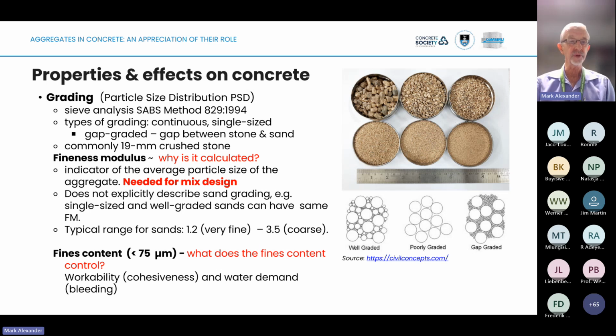We then have fineness modulus. This is an indicator of the average particle size. We need it for mix design. But note that it's not an explicit measure. You can get fineness moduli for different sands of the same value, but they might have vastly different gradings. And so it's a general sort of guide, but it's not an exclusive one. Generally, we try and work between somewhere around 1.2, which is a very fine sand, up to about 3.5, which is rather coarse, but I've seen many cases where that goes up to 3.7, 3.8, or something like that.